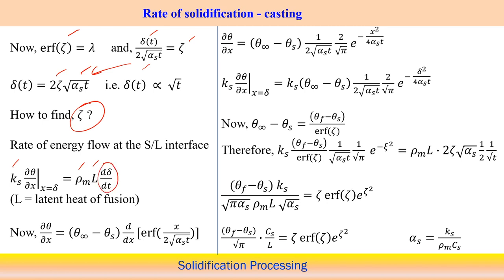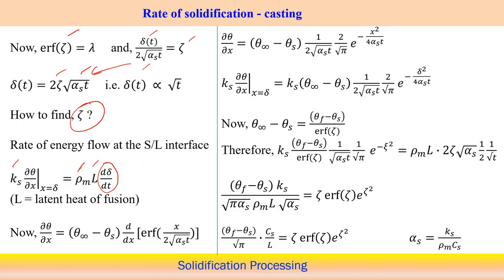It is basically the velocity of the solidification depth in this particular case, at what velocity the solidification front is moving. So rho m L d delta by dt. Basically we are balancing, and the cross-section area is the same in these two cases, so they cancel each other from both sides. So rho m L d delta by dt equals this one, where L is the latent heat of fusion.